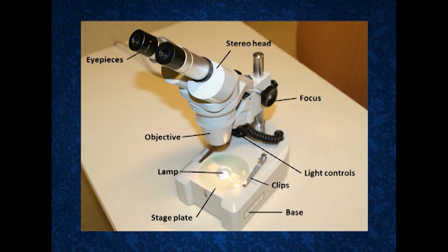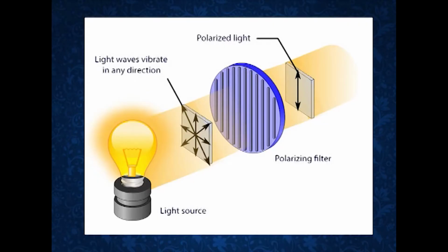The questioned and the reference fibers must be viewed simultaneously or side by side by the fiber examiner and at the same magnification in visible light and alternative lighting, for example, polarized light or fluorescent light, which, though not necessary, is recommended if the equipment allows. For some analysis, for example, in testing for solubility, it may be necessary to place the questioned and the known fibers next to each other on the same slide or in adjacent wells of a spot plate. Precautions should be taken in case of loose fibers such that the source of the fiber is not confused with some other sample.